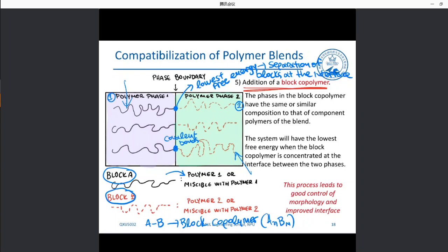This concept, as I told you, is used widely in incompatible blend systems and usually leads to good control of the morphology combined with an improvement in interfacial adhesion, an improved interface, and hence good mechanical properties. Remember that mechanical properties are the properties most significantly affected by the properties of the interface. Of course, the majority of physicochemical properties are affected by the interface, but mechanical properties are the ones most strongly affected by interfacial adhesion and generally the properties of the interface.